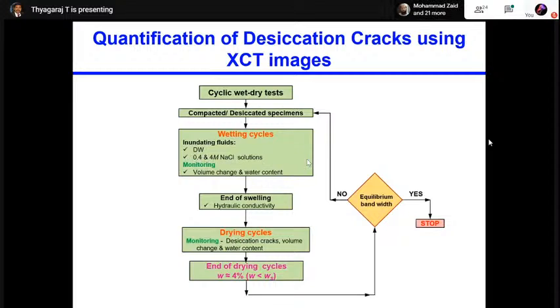During wetting, we monitored the volume change and water content. And after wetting, we dried it. At the end of wetting, we measured the hydraulic conductivity. Then the same sample, we dried it, and we monitored the desiccation cracks during drying and at the end of drying, as well as water content. Once the water content is below the shrinkage limit, approximately 4%, we said that there will be no volume change. We stopped and went to the next wetting cycle. So we repeated until the equilibrium bandwidth had happened.